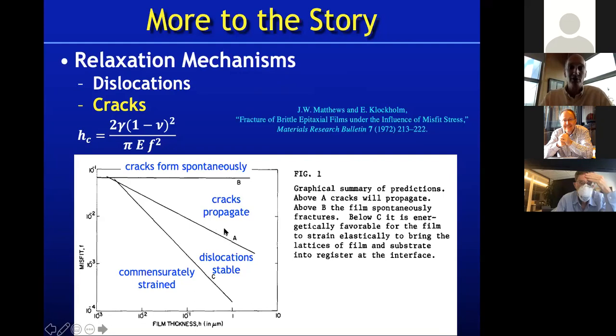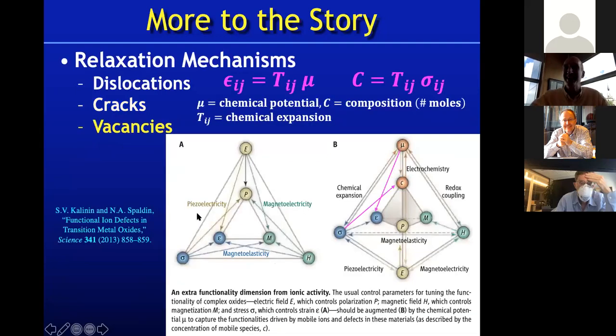Matthews also calculated at what strain, that's this line B here, cracks should spontaneously form. Okay, and there you can see, very well, from my perspective, very large strains, but it's important to keep these relaxation mechanisms in mind when you're thinking of how you're going to access this ground state. This is the reality that kicks in.